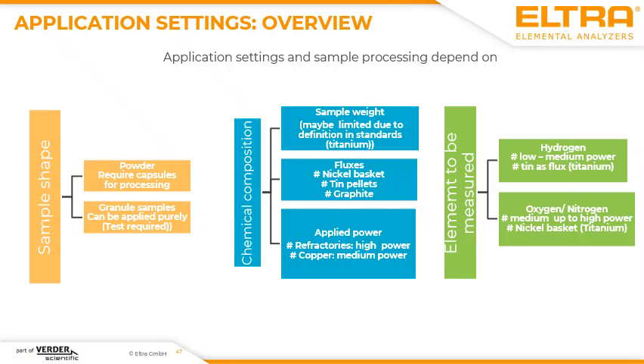Then please have a look at the chemical composition of the sample, or the approximate chemical composition, because this influences a lot of single steps. On the one hand, maybe the sample weight is reduced when you have, for example, titanium-based or refractory-based samples, and then you cannot apply more sample weight than 100 milligram. When you have samples which are new for you, you also have to consider a different chemical composition, and maybe you have to take care of nickel baskets to make sure that the analysis is correct.